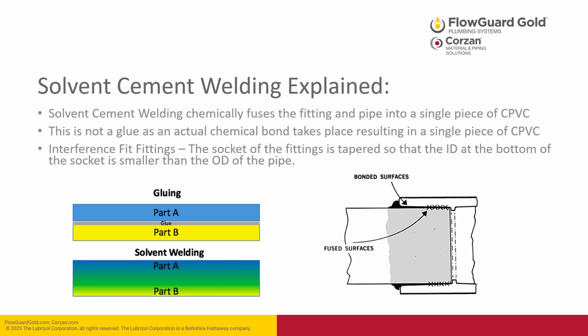Solvent welding is an actual weld that chemically fuses the pipe and fitting into a single piece of CPVC. This is not a glue because an actual chemical bond takes place. This all relies on the use of interference fittings. The socket of the fittings is tapered so that the internal diameter at the bottom of the socket is actually smaller than the outside diameter of the pipe. This forces the pipe and fitting together and allows the solvent weld to be completed.